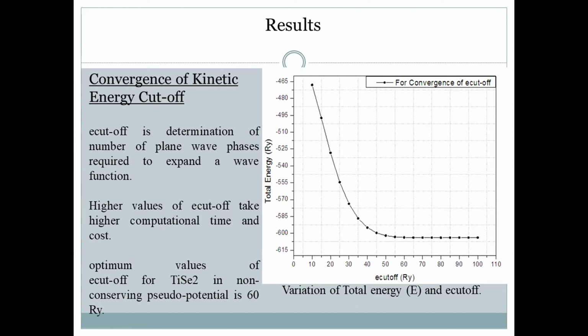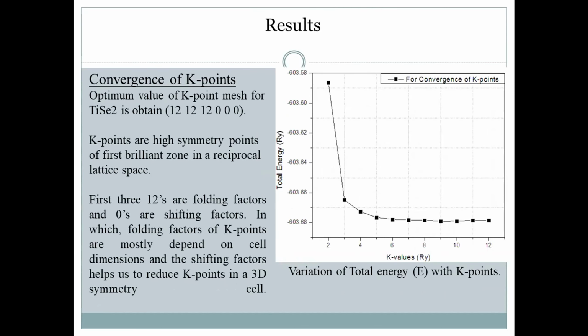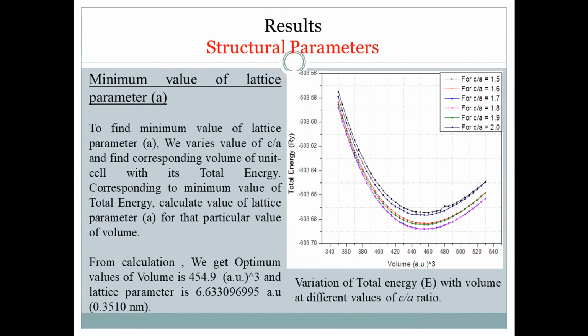After convergence of the kinetic energy cutoff, we move to convergence of K points. K points are high symmetry points in the Brillouin zone. For TiSe2, we have 12, 12, 12, and 0, 0, 0 K points. The first three K points represent the folding factors, and the last three represent the shifting factors. After K points, we calculate the minimum value of the lattice parameter at different volumes. We consider c by a, the ratio of lattice parameters along different axes. We consider c by a from 1.5 to 2 and find the minimum volume and minimum energy for TiSe2.